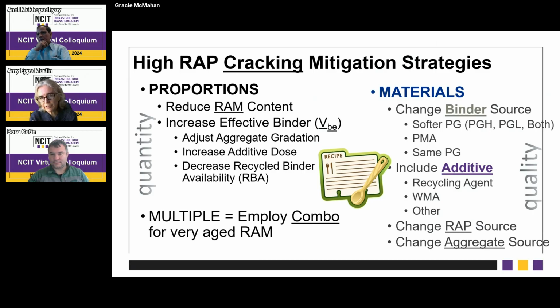And something that's more difficult to do is to change the RAP source and the aggregate source. Usually that's tied to the location and the specific contractor and the availability of materials locally. The other thing we can do is change the recipe, right? The proportions of those materials. So a big thing that people do a lot is to increase the effective binder, which means the binder that's not absorbed into the asphalt, but available for binding and coating our aggregate particles together. So a lot of times the aggregate gradation is adjusted. We can also increase any additive doses.